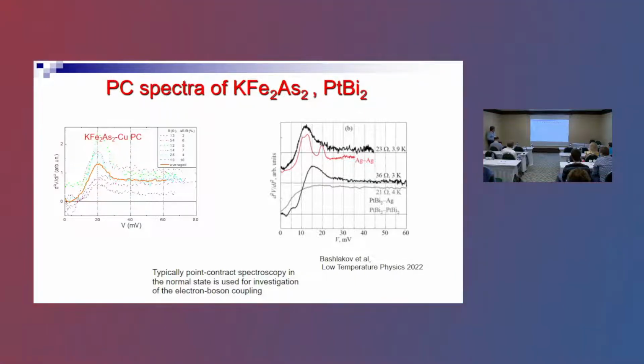This is typical of what was done, for instance, for iron-based superconductors with copper point contact, and we see that the strongest feature is at 20 millielectron volts. If you look at the bosons there, it basically corresponds to a bosonic type, namely with this peak, and that was the reason.